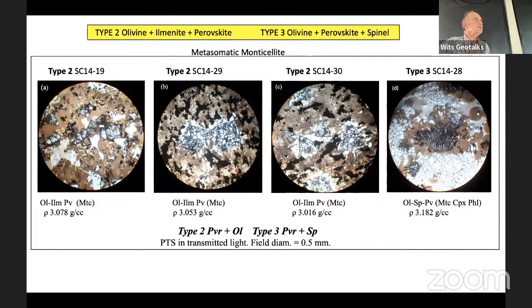On cutting and polishing a thin section, here was the other big surprise, this euhedral, absolutely magnificent, in some cases clear crystals, in other cases saturated with olivine. But look at this one here, look at that. This is the field of view, but this is a perovskite. And then type two, so this is perovskite plus ilmenite plus olivine. The host is olivine, and here the host is olivine plus spinel plus perovskite.